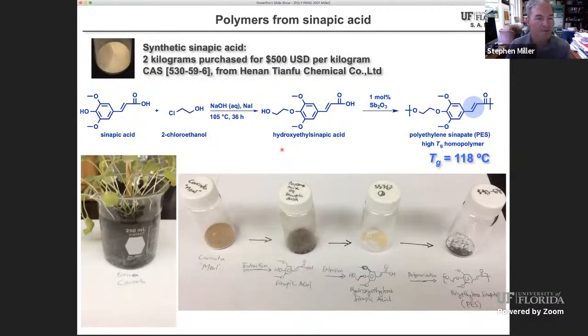So here's a sequence that we've done to make a polymer from sinapic acid. We take the sinapic acid, we extend it with chloroethanol, which is not the greenest way to do it, but it is a way to do it. And we make this hydroxyethyl sinapic acid, which we can polymerize with antimony oxide, and we can make this particular polymer.